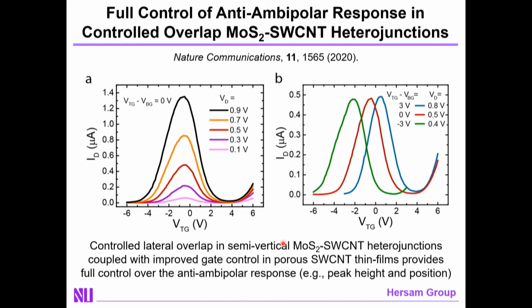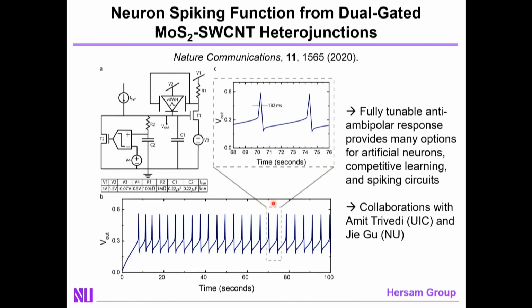The beauty of this device, though, is due to the asymmetric screening and the fact that we have two gates, that we can fully tune the Gaussian response. We can tune the peak height, the peak position, the peak width at will. And the reason this is of interest is that when you have a Gaussian output characteristic which is fully tunable, you can now realize highly nonlinear voltage spiking responses in relatively simple circuits.